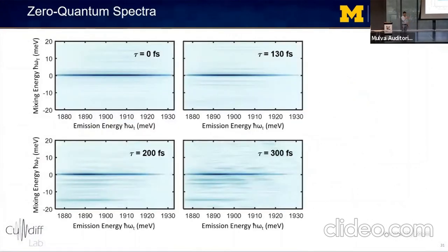So these are the zero quantum spectra for collinear excitation, where we see side bands due to vibrational coherences. And one thing that indicates that they're vibrational is the asymmetry of the side bands, whereas in the electronic side bands, you see that they're symmetric around the zero energy line. And if you look at the zero quantum spectra as a function of the first time delay tau, we see that the sidebands only come in after a certain time delay, which might indicate polaronic dynamics. And if we look at the zero quantum spectra as a function of temperature, we also don't see some dramatic crossover. So this is a very interesting topic, but I don't actually have any data that indicates any of this.